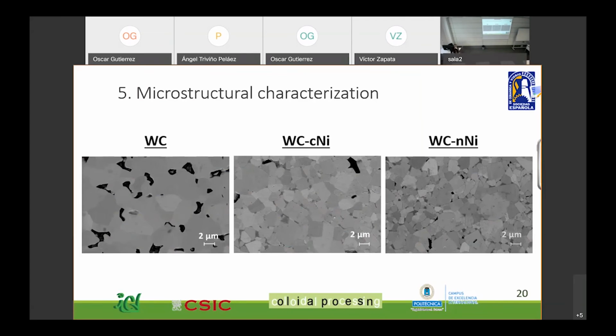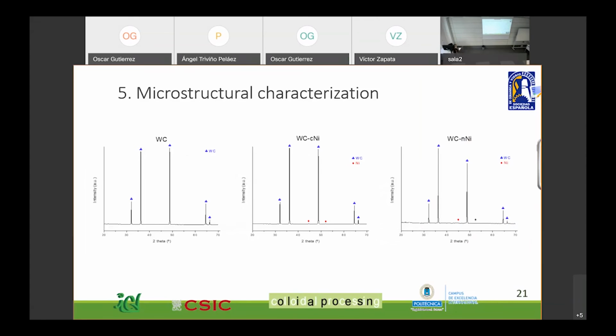We can also notice there is a huge difference in the mean grain size in these three samples, and they are actually very, very small in the case of the mixture with the nanometric synthesized nickel. After that, we decided to carry out an XRD study, and we could just notice there is no other detected species but tungsten carbide and nickel materials, which can also mean that there is no intermetallic formation or solid solution in these three samples.